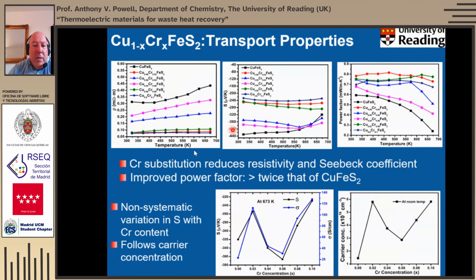However, the fly in the ointment is that we find if we take the Seebeck and resistivity at a given temperature, and we're choosing 673 here, we see that they vary in a non-systematic way with chromium content. We might have expected them to vary steadily as we increase the amount of chromium, but instead of that, they follow this sort of double zigzag type curve, and that mirrors the changes in carrier concentration.